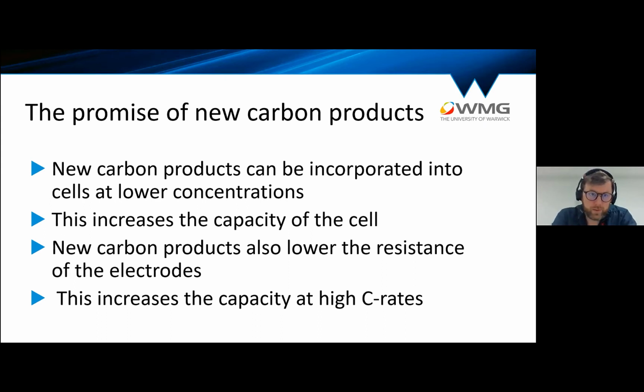New carbon products are being developed the whole time to be incorporated into the cell at much lower concentrations. While this doesn't, I suppose the next bullet points can be interpreted slightly wrongly, in that it doesn't increase the theoretical capacity, it increases the capacity retention at set discharge rates. And obviously it lowers the resistance of the electrodes. So the conductivity that you get from the carbon additives that are being put in allows a reduction in the overall resistance, which then allows the retention of your capacity. Hope that makes sense. If not, please quiz me.